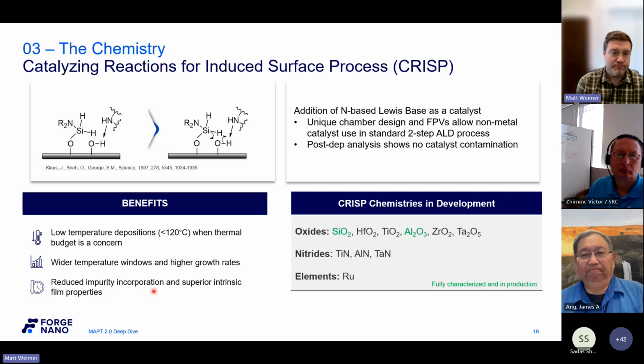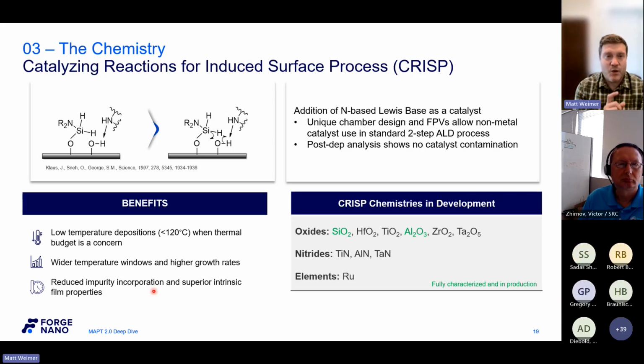Yeah, great point. I'm going to mention a couple of brief things and then I'll move on. One of the things that we do differently is we prefer to include our catalyst with our conversion step. Instead of doing a 3-step ALD process, which gives you an even longer cycle time, we try to combine the catalyst into the conversion step. So we still have just an A-B, the typical ALD process. Because our valves move so quickly, I can finely control how many moles of catalyst and precursor I'm putting in the chamber. One of the problems with catalysis is you can poison the surface. Because we have that fine control, we know where those limits are, so we know when we put in too much and we can dial it back.